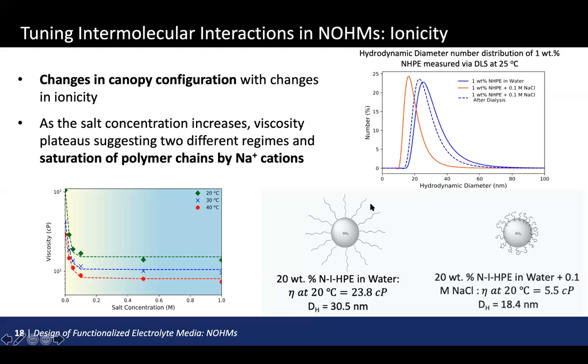So in a water-based system with no added salt, those polymers are able to swell, which leads to this increased size of NOHMs. However, when we add those ionic species, they interact with the polymer canopy, and that leads to those polymers collapsing, and we see this decrease in size. To probe this further, we did a viscosity study where we continued to add salt and investigated at what point the viscosity will no longer decrease. And again, we see that there's a critical concentration where viscosity remains constant.